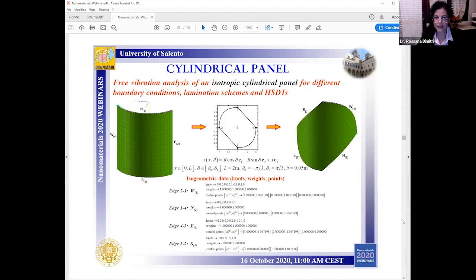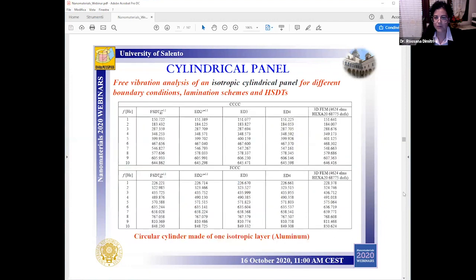As further application, let's consider a cylindrical panel cut by this general shape defined by 2 curvilinear edges and 2 linear ones to yield the complicated geometry you can see here on the right side of the slide, which is made of one isotropic layer, I mean an aluminum, for 2 different boundary conditions, where we compare the 3D FEM-based solutions with the 2D ones as provided by 2D higher order formulations.